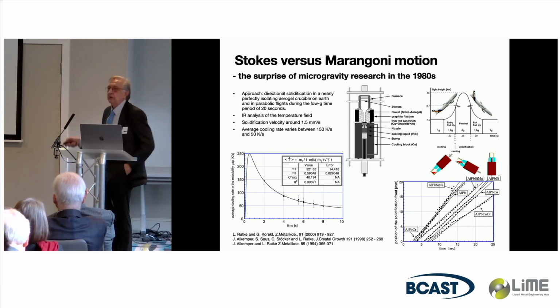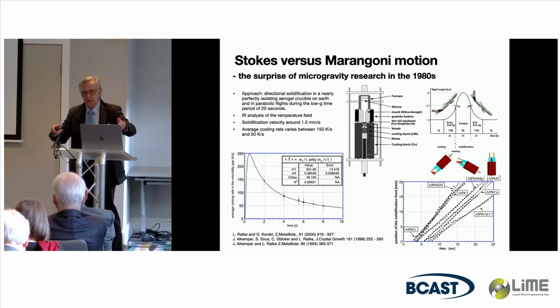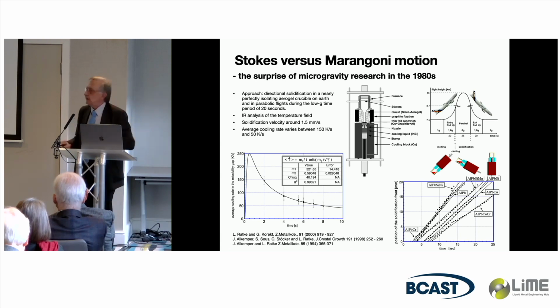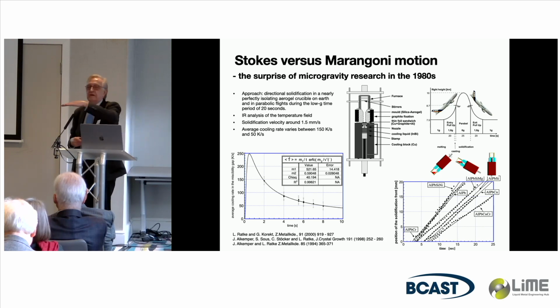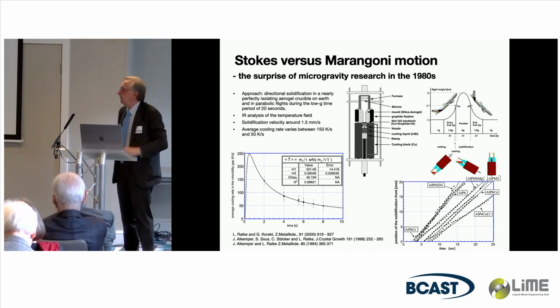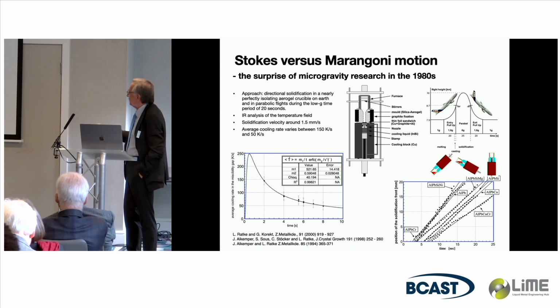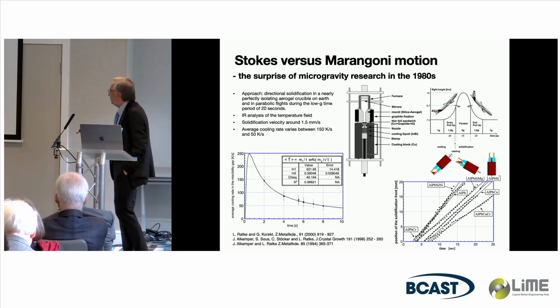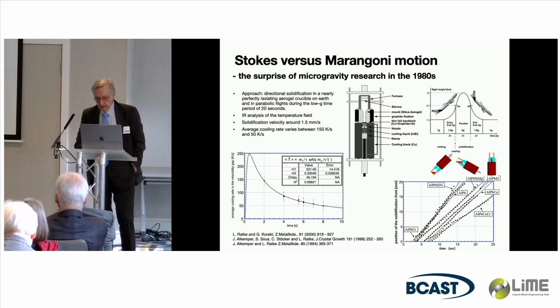This is measured optically. We have an infrared camera. You measure at the surface temperature, and you can say, yeah, but the interior will be different. No, due to the fact that aerogels have a very low thermal conductivity, you just have radiation heat losses. You can wonderfully measure that, and you can, by numerical simulation only, show that the isotherm is almost flat. So it has a bending of maybe 20 microns. That's it. So we have cooling rates in the 50 to 100 Kelvin per second range. And what you observe is exactly then what you would have expected.